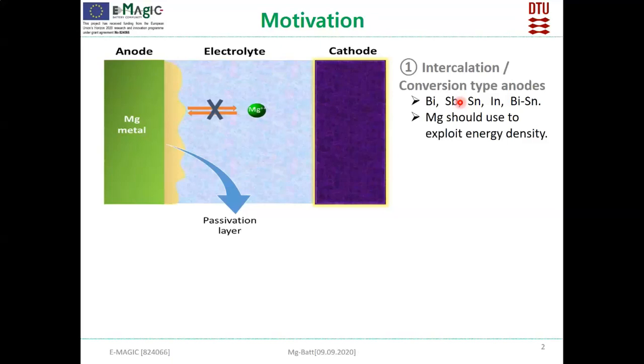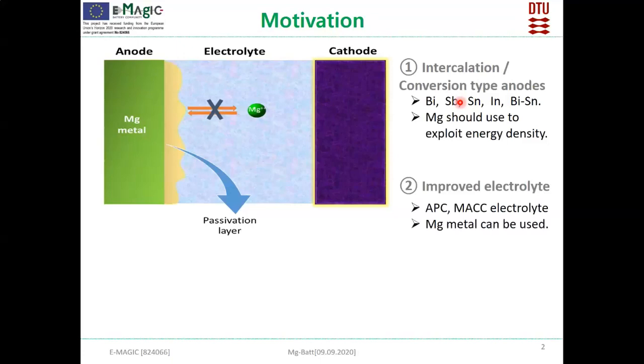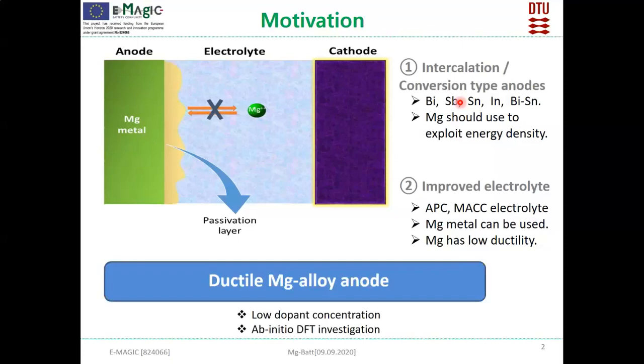The other solution is to use improved electrolytes, like the APC or MACC electrolytes. Then we can use magnesium metal. But then the problem is that magnesium has low ductility, since the hexagonal crystal system of magnesium is inherently brittle. So the solution is to use a ductile magnesium alloy anode. A ductile magnesium alloy anode refers to a low dopant concentration. The dopant concentration we add should be very low. Then only can we completely exploit it in terms of energy density.